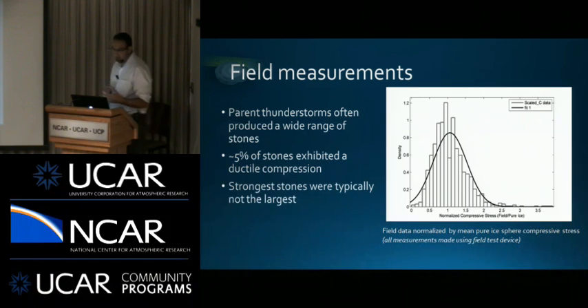Now, 5% of the stones we've actually collected in the field, even at our strain rate that would produce a brittle failure in pure ice, simply compressed and held their shape. Whether these are the spongy stones that the literature talks about, I'm unsure. But even at that strain rate, they simply compressed and held their shape with no noticeable fracture. And you can actually see that if you look at the raw trace of the compressive force information. And in general, the strongest stones, the hardest stones, were typically not the largest. So some of the smaller ones actually had some of the larger compressive force values. So kind of interesting to see that.